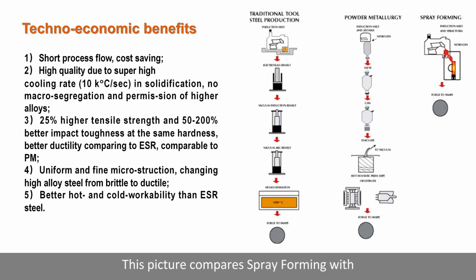This picture compares spray forming with traditional steel making, VIM, ESR, and VAR, and PM, powder metallurgy, of high-performance steels. It used to be recognized that the PM process should make the best high-alloyed steel. Now, our R&D reveals that PSF makes steels as good as PM, but with a much shorter process flow and much better techno-economic benefits, while being pollution-free and energy-saving.